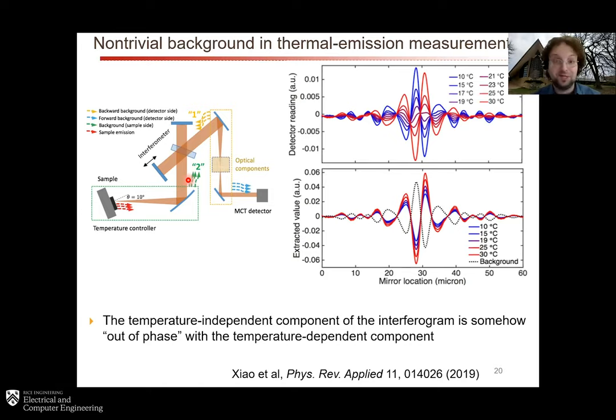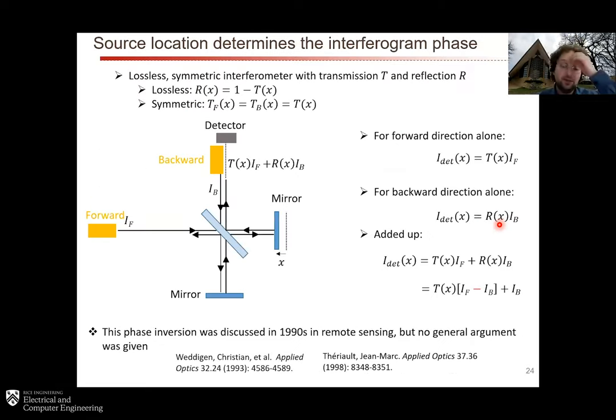This is not some sort of destructive interference phenomenon that's happening. In this case, it's that the interferograms are out of phase rather than the optical waves being out of phase. And so you can see that in a little bit more detail. I'm not going to go through this with a great degree of detail, but actually this phase inversion of the interferogram, it turns out, was not known